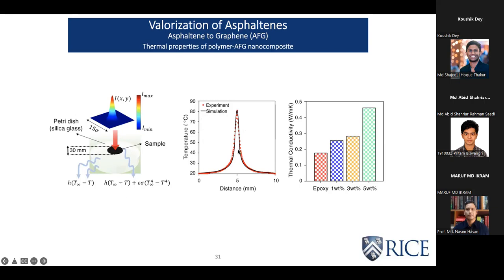the experiments. And when we had this type of fitting, the conductivity that was used for this fitting was taken as the thermal conductivity of epoxy. And this thermal conductivity is also well within the range that is reported for that particular type of epoxy. And using the same method, we reran the simulation for nanocomposites also, the 1-weight%, 3-weight%, and 5-weight%, and we saw an increasing trend for the thermal conductivity. So this means that with increasing AFG, the thermal dissipation behavior improves, as well as the thermal conductivity improves.